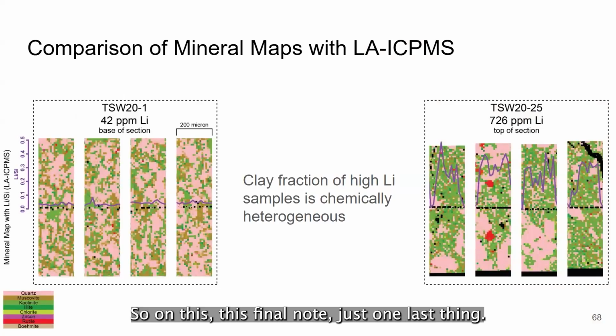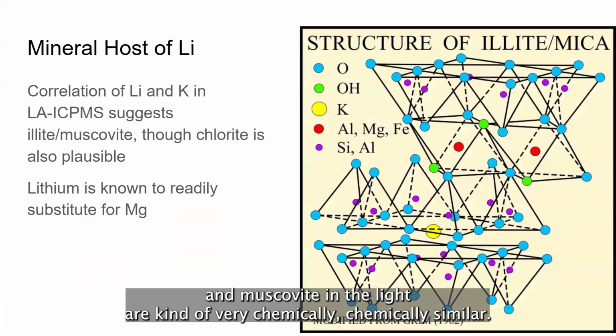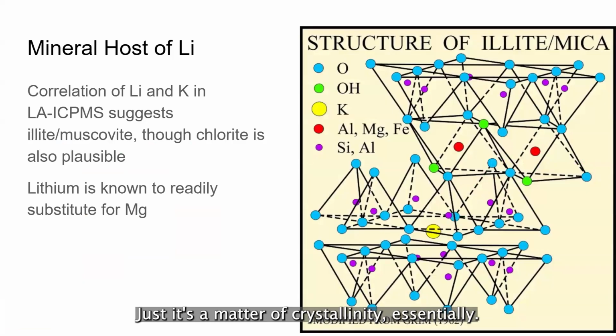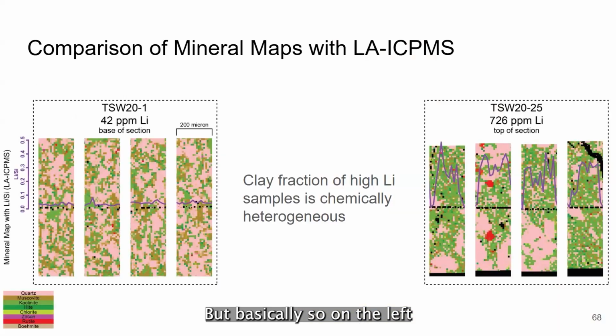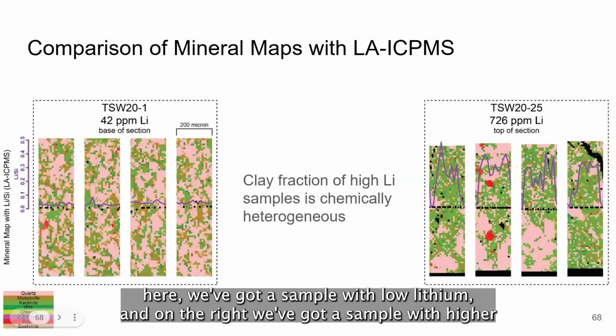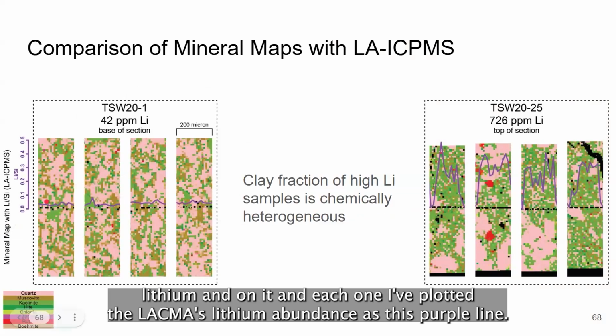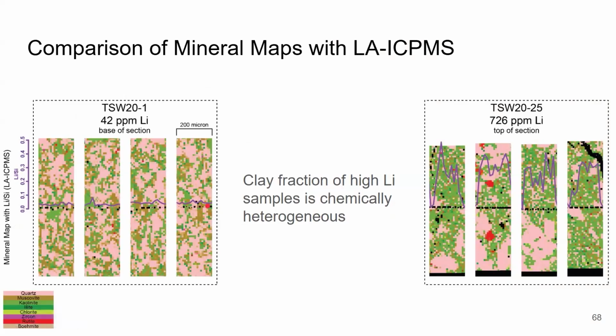So on this final note, just one last thing. It's not just looking for illite, mica, or muscovite. And muscovite and illite are very chemically similar. It's just a matter of crystallinity, essentially, like how well developed the crystal is. But basically, on the left here, we've got a sample with low lithium, and on the right, we've got a sample with higher lithium. And on each one, I've plotted the LA-ICP-MS lithium abundance as this purple line.